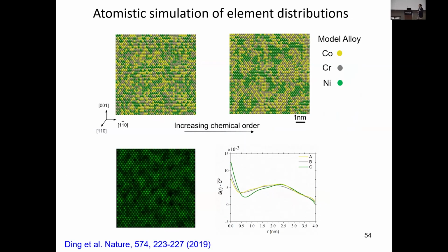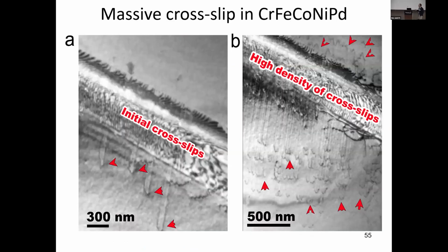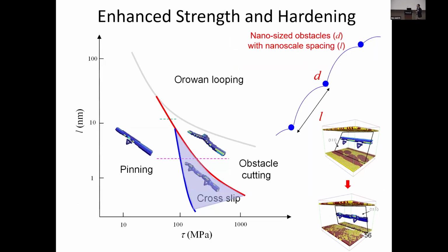We also did a Monte Carlo simulation for this modeled ternary alloy system to directly show that we can produce this nanoscale compositional fluctuation, the so-called nanoscale clustering phenomenon, and the simulated TEM images are consistent with the TEM experimental results. And what's their impact on the mechanical behavior? We use in situ TEM deformation experiments to study the deformation behavior in real time. You can see this very dramatic, massive cross-slip out of this primary deformation band. This kind of behavior has not been seen in any other conventional FCC alloys. So that clearly shows the impact of nanoclustering in these high-entropy alloys.